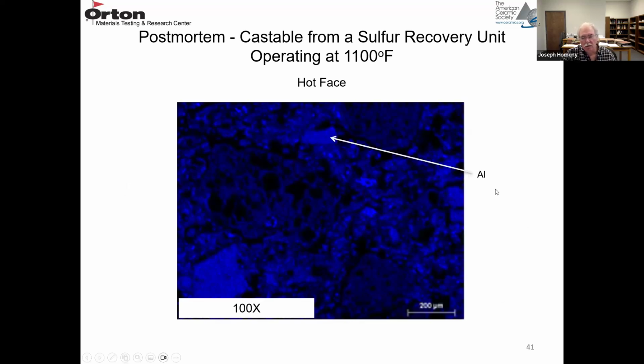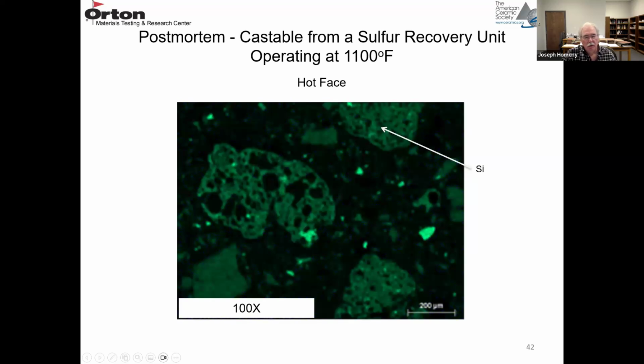If you do the mapping, in blue, that's aluminum. Here's one of the coarser aggregates. And then apparently the aluminum oxide in the matrix was a little bit higher alumina content, so it's a little bit brighter on the finer material compared to the coarser aggregates. And you can see the coarser aggregates in green here, the silicon. So they're a little brighter than in the matrix. And these very bright green spots have to be either quartz or maybe even cristobalite.